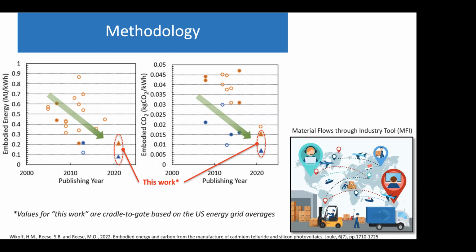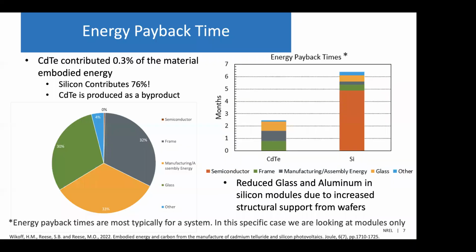And again, I'm going to highlight we were doing cradle to gate, so we only looked through the finished manufactured product. And you can see, obviously, our values are a little bit lower than some of what was in the literature, but we are also at least 3 years newer, so we're using more state-of-the-art, and a lot of things have changed. There's been a lot of material reductions and other things. So we felt fairly confident that we were starting at a baseline where there was nothing crazy that we were doing. We were confident in our tool, confident in our recipes. And so starting from that standpoint, we ran the numbers.